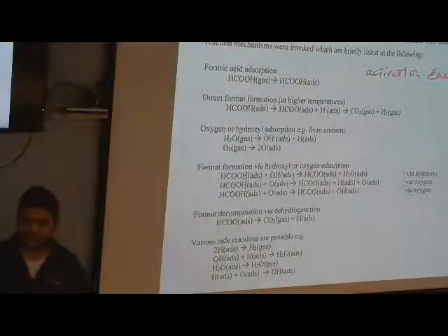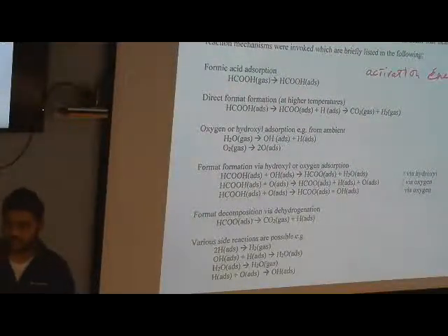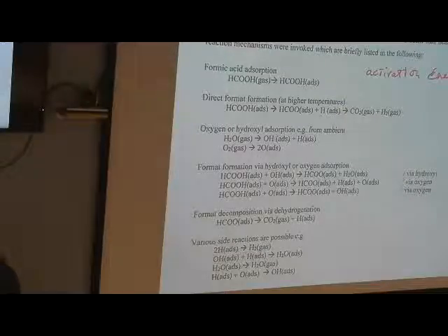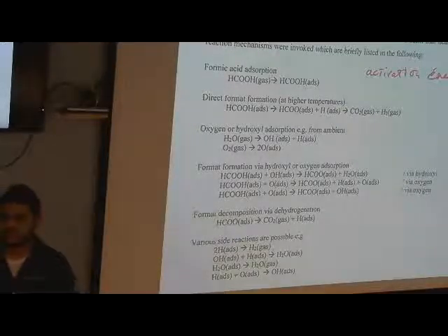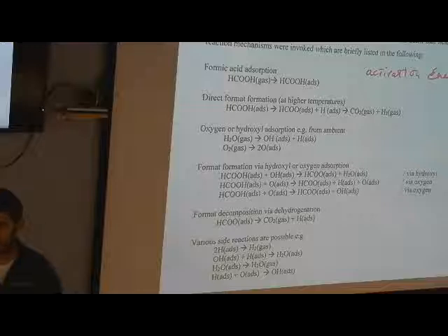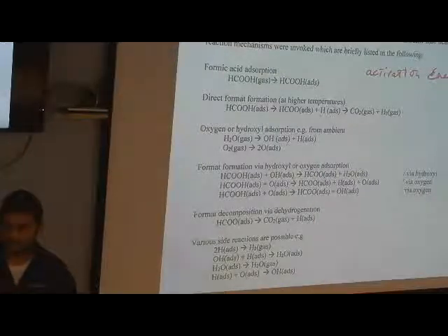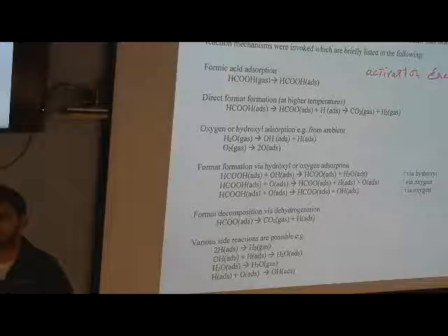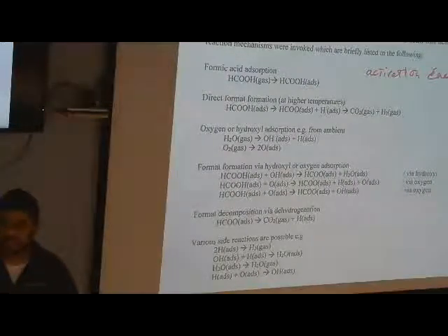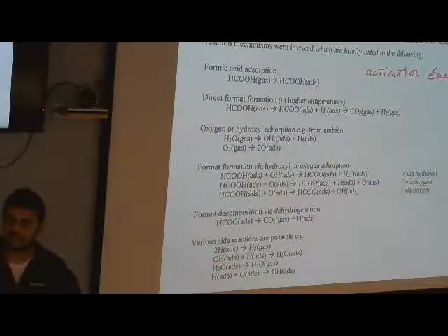Right, yeah. But if it has the right temperature, here we have the activation energy. When you have the submonolayer coverage, we needed like 600 Kelvin for the decomposition, and up to that temperature it was stable in vacuum. That means we don't have that kind of huge hydrogen source, but still without that hydrogen source it was possible to desorb that one.